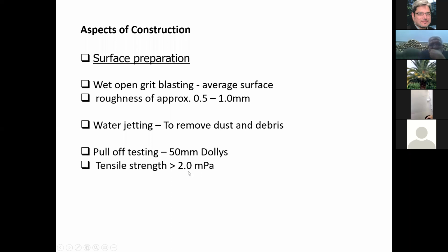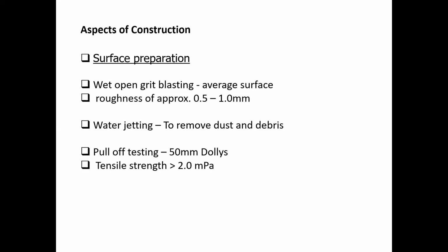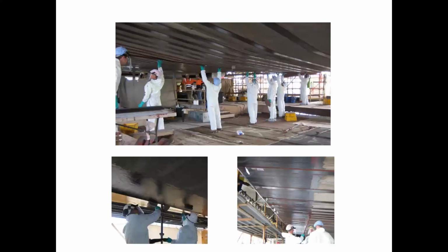According to ACI, the minimum tensile strength is 1.5 MPa, but for this particular bridge, we upgraded that. We required a minimum of 2 MPa. And the result of the testing on the bridge gave us between 5 to 6 MPa, so this was no worry whatsoever.